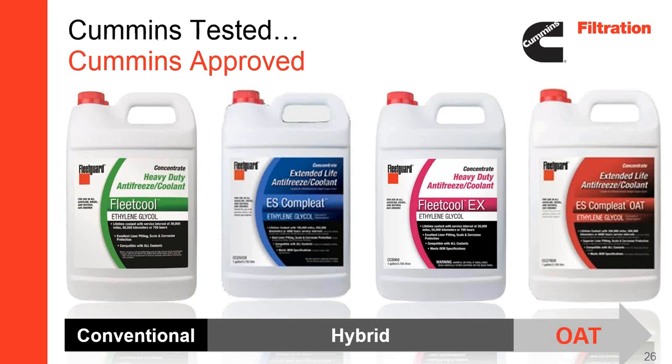Okay, a question coming in. What is NOAT, N-O-A-T? So NOAT is nitrited OAT. So that would be a coolant that's got a lot of organic additive technology, maybe more than your typical hybrid product, but it also has nitrite in it. And nitrite can be one of the additives that's not a great choice for environments that have a lot of aluminum, especially aluminum heat exchangers. So it's an OAT type coolant that has one of the older conventional type additives in it.